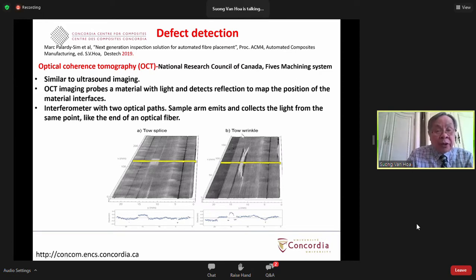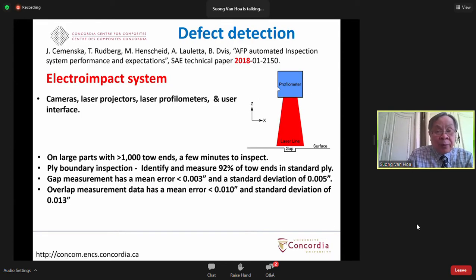And from the industrial side, from the Electroimpact publication in 2018, they developed a system where they use a laser profilometer, with a projected laser line on the surface of the substrate. With this, they were able to detect more than 1,000 tow ends in a few minutes, and they identified 92% of the tow ends in the standard ply. So this system was able to detect the presence of defects effectively within a short time.